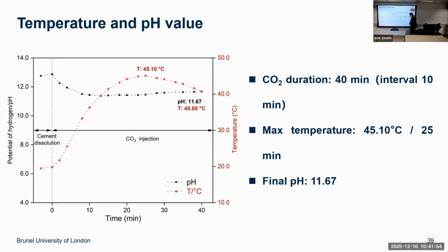We started at room temperature, around 20 degrees, and the final pH can still be maintained at 11.7. I know that for normal concrete the pH is around 13. It doesn't drop too significantly, and you don't want it to drop too significantly. That is a good thing for concrete, and it will have a passive film which protects the reinforcement from corrosion.